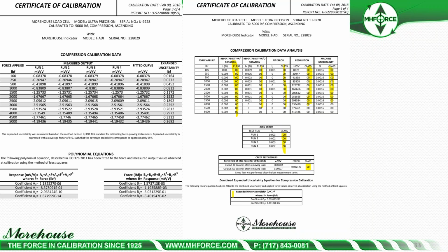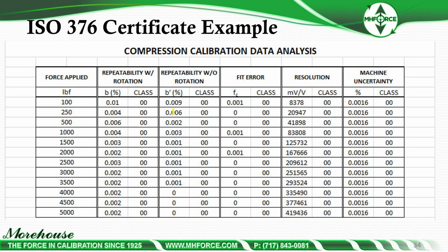And then an expanded uncertainty equation is reported, which is nice. So you can use this equation for the expanded uncertainty at any point during the force range, and it will tell you what your actual uncertainty is. So if you're issuing reports to customers or you're out in the field and you're using an ISO calibration, you will know your expanded uncertainty per ISO 376. And if we look at these in higher detail, you can see the actual numbers, 0.01, 0.004 per point. As I said, every one is tested per the load point, and this is why that 5% point is recommended.